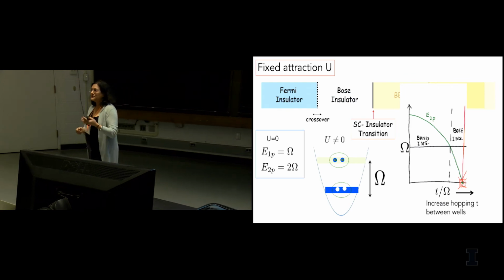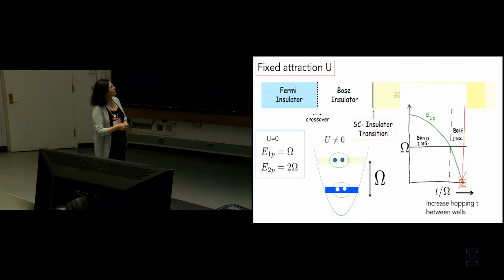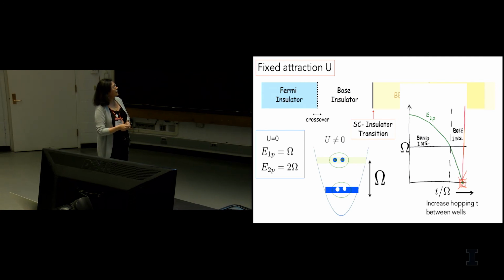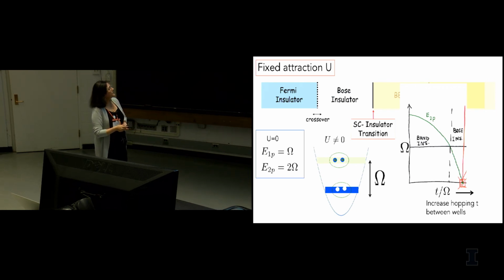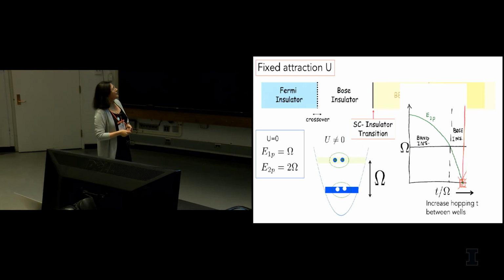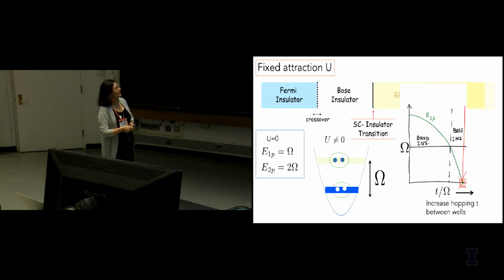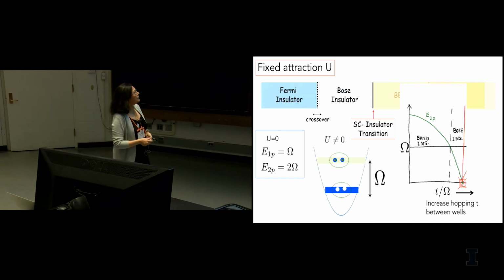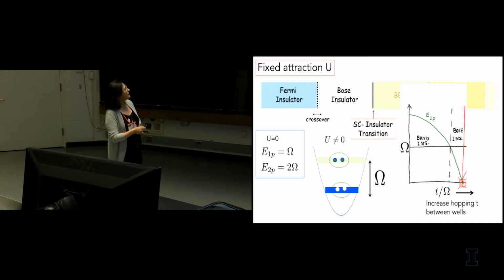We heard about excitons earlier. Those were essentially an electron-hole pairing. Now I'm pairing these holes by themselves and these electrons, so I'm getting these Cooperons. What is shown here is the binding energy of these Cooperons. Initially, when the attraction is 0, the binding energy would just be 2 times the energy to create 1 electron-hole pair. But as the attraction is increased, or you can think of increasing the tunneling, it's possible that the 2-particle binding energy now becomes lower than the band gap, the single particle energy.